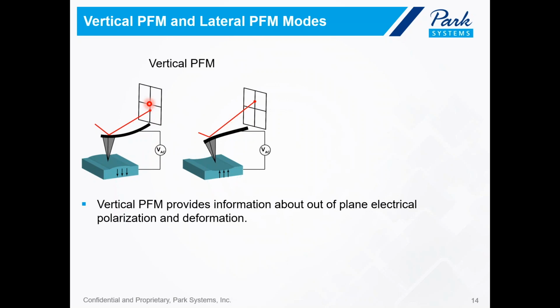So the first mode shown here is vertical PFM, where one can imagine that the laser will deflect vertically as the cantilever deflects up or down in response to the material which is changing as a result of its piezoelectric properties. So vertical PFM provides information about out-of-plane electrical polarization and deformation. Out of plane meaning perpendicular to your sample surface.